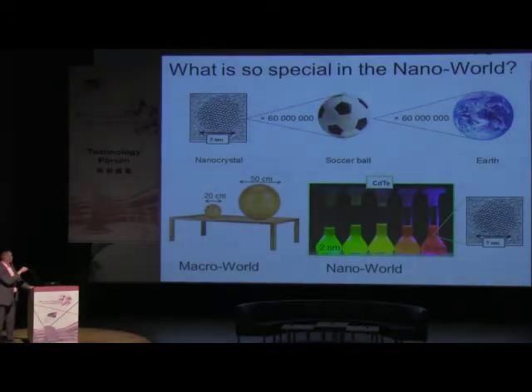The nanocrystals we are working on look like shown here. These are crystalline particles. They are tiny, about 60 million times smaller than a soccer ball, which is roughly the same ratio as from the soccer ball to the Earth. What is very nice about these tiny objects is that we can control their emission by changing size. This is called the size quantization effect. If we make them smaller, they emit more energetic light, which means for this example of cadmium telluride that we can tune emission from green to red if we change size.